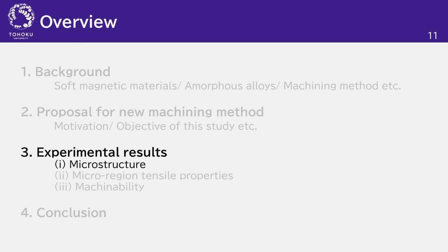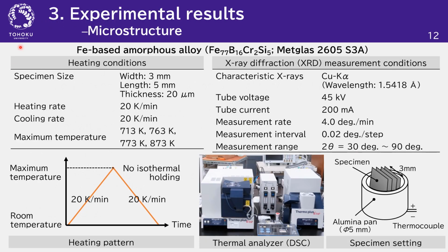Let me now move on to explain the results of the experiment. First, we tried to create different microstructures in the amorphous alloys. We used Fe-based amorphous alloys for the experimental material. Amorphous alloy changes the microstructure sensitively to temperature. Therefore, in this experiment, we used a DSC apparatus for heat treatment. DSC is a thermal analyzer enabling precise temperature control.